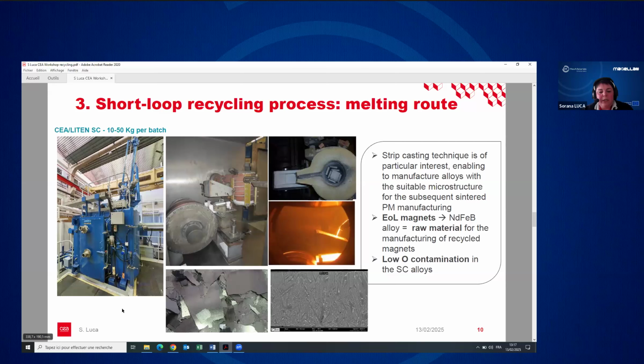Here you can see some pictures of the strip cast equipment which is installed in CEA-Liten, which enables to fabricate batches between 10 to 50 kilograms of alloy. Here we have the copper roll, rotating roll, and here you can see the melted alloy which is poured on this copper rotating roll.